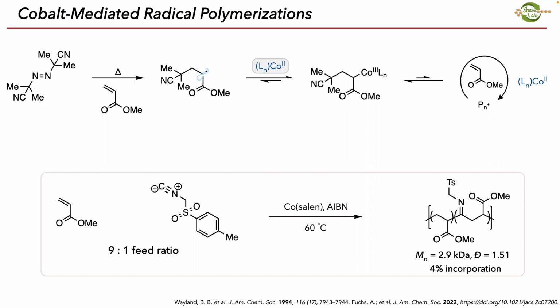So Layla tried this chemistry, now adding a cobalt complex, and again, using AIBN, same feed ratio. She sees similar levels of incorporation, but now we get a really small polymer, and we still don't have good control over the dispersity. We're targeting levels of 1.1 or 1.2. We're seeing broad dispersity and low molecular weight.